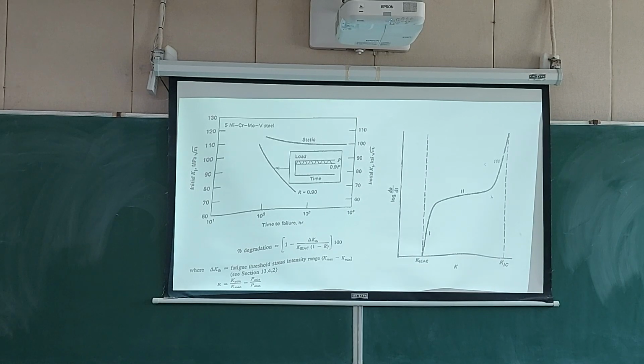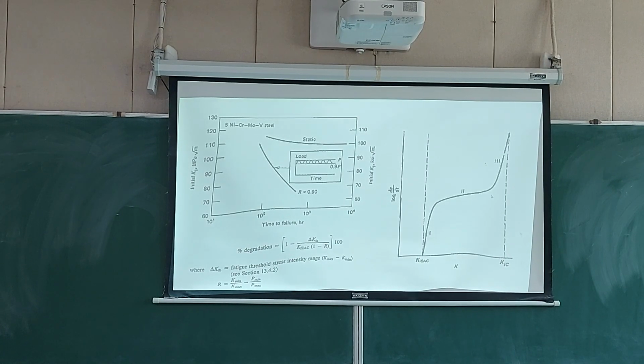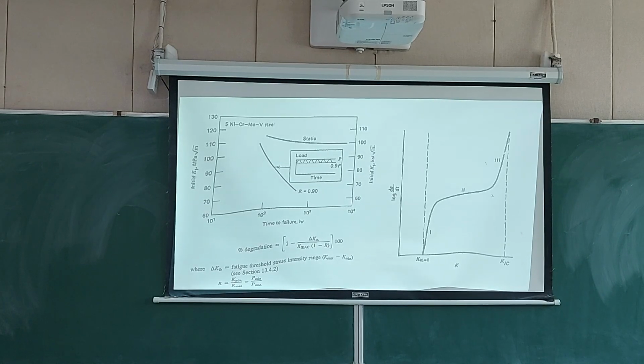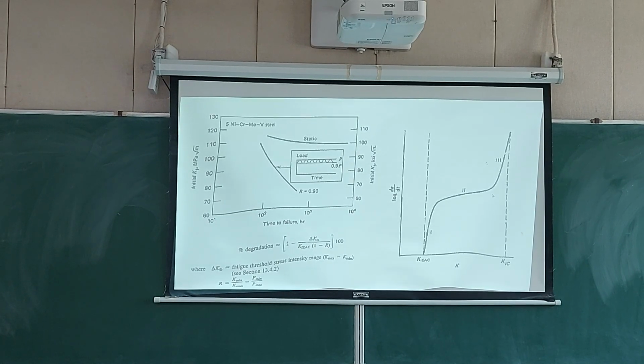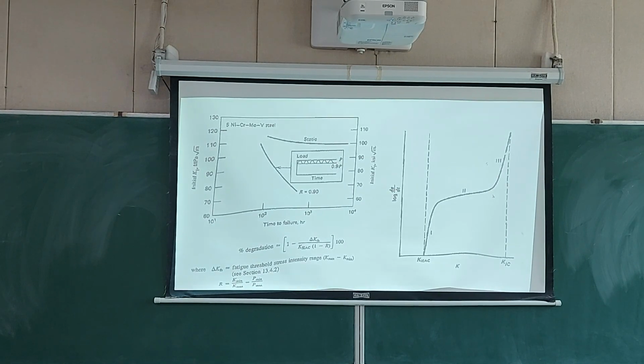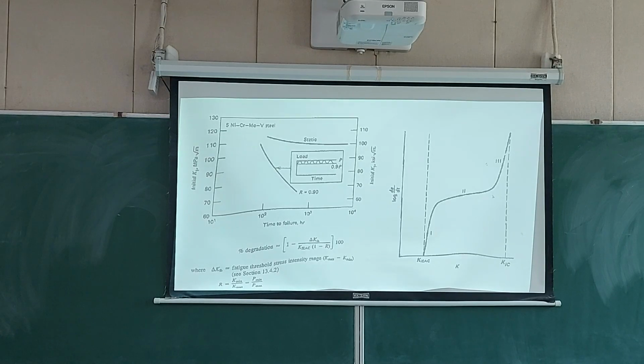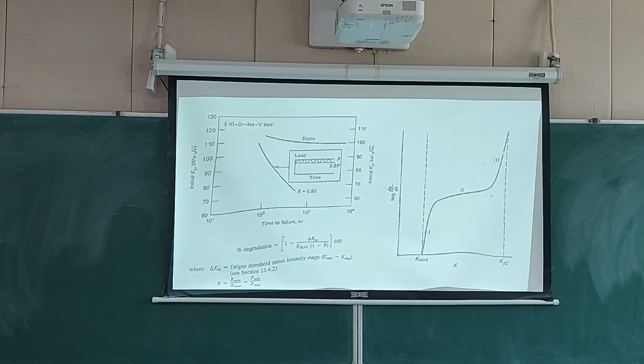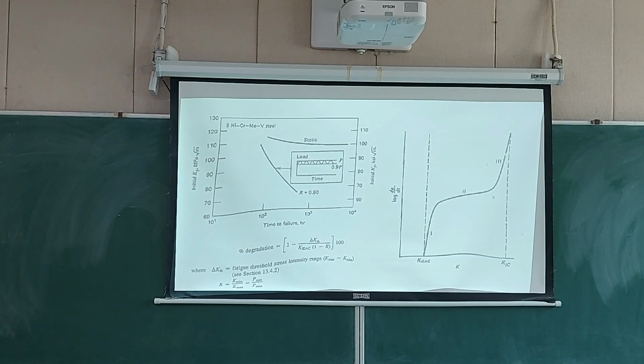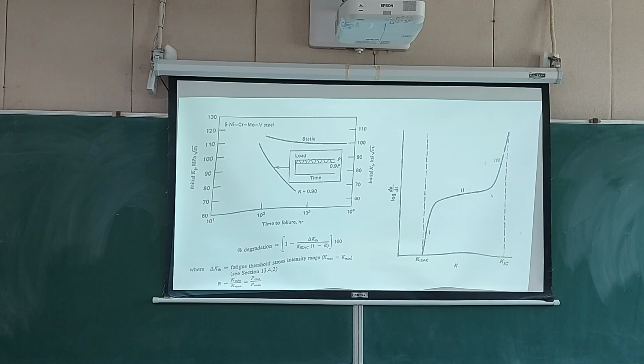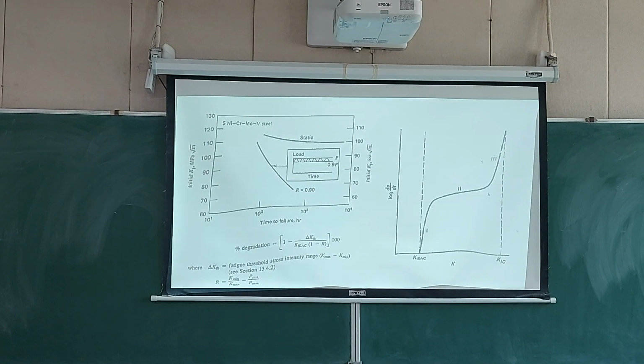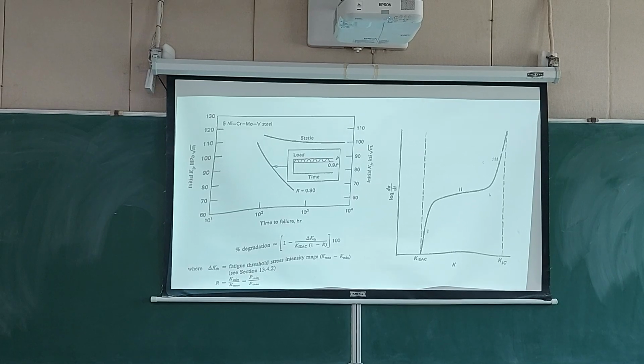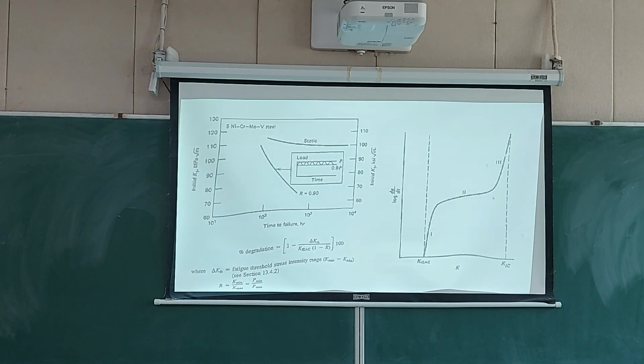On the left hand side, what you see is the effect of cyclic loading on it. So the scenario can be further complicated. It can be creep, creep fatigue, or environmental assisted cracking in the presence of cyclic loading. You can further complicate it by putting it at high temperature. A very small amplitude of loading has been applied on the curve, which has a steeper slope that is lower than the static curve. The maximum load is P and the minimum load is 0.9 P, so R is 0.9 in this case, and you see a drastic change in the K versus time to failure plot.